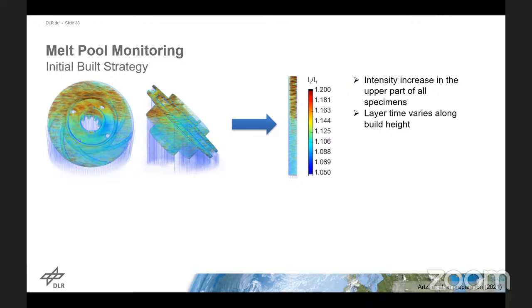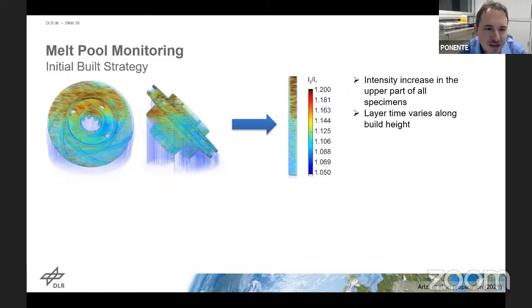Yes. Fine. You can see here that towards the top of the impeller, the intensity is a lot increased. So it's getting hotter when the final part of the impeller, the top part, is being manufactured. And the simple reason is the cross section per layer. Here at the bottom parts with the supports and so on, you have a lot of area that you have to laser, which takes a long time.